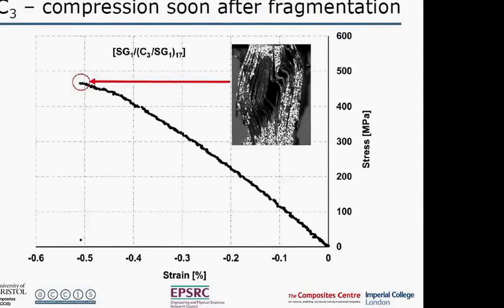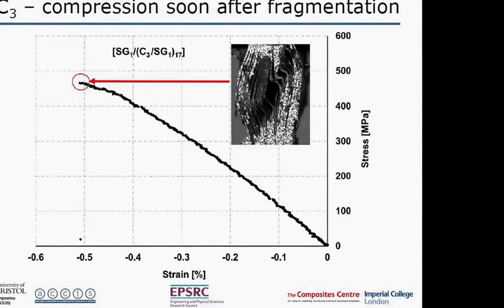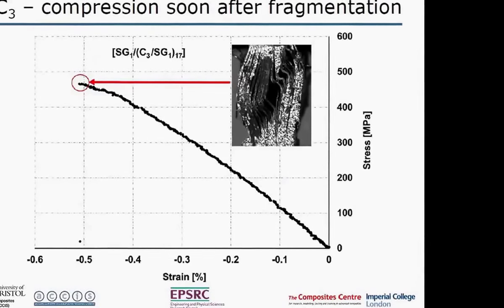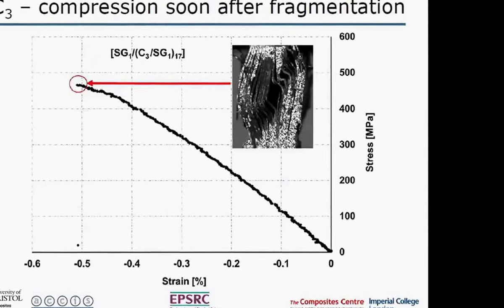So what's happening in those cases there? When you see it on this case here with the 3 carbon plies, then at this point here, you get a catastrophic failure. It's failed in compression, and it's also extensively delaminated. A bit hard to see which happens first in that case there. Basically, more or less as soon as it fragments, the whole thing fails.